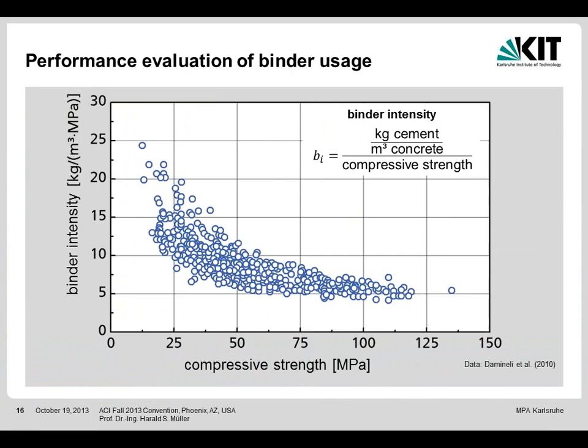But the cement is a decisive part. Now we can consider what to do. The thing is, use as low cement as possible. We have to look at the binder intensity. This means the amount of cement per cubic meter of concrete divided by the compressive strength.